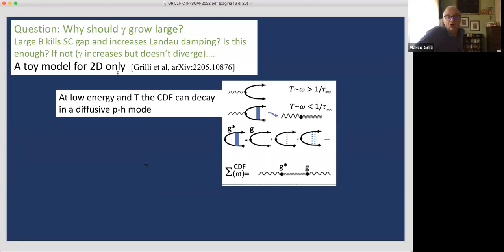So we thought of a toy model, just as an example, which is only valid in 2D, to provide, at least in one case, an example of a situation in which we can realize this increase of the Landau damping parameter gamma. The idea is simply related to the fact that in any standard metal, even a clean metal, you have some impurities. And if you have particle-holes of low enough frequency and at low enough temperature, smaller than the scattering rate due to impurities, then these particle-holes do not propagate ballistically, but they start to diffuse, scattering with impurities. If you make an infinite resummation of these impurity scattering processes, you end up with a diffusive pole, which can dress the charge density fluctuations. So this is the idea.